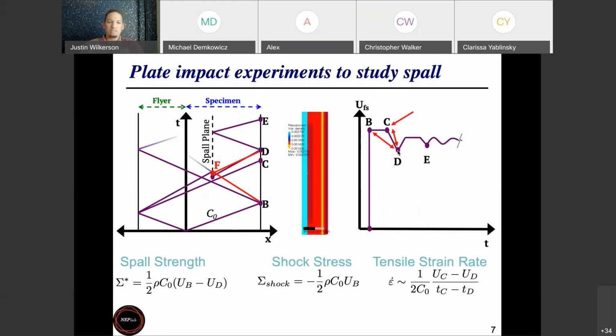And so we can vary a number of conditions to study spall strength under different conditions. Obviously we can launch the flyer plate at different velocities, and higher velocities are going to generate higher and higher shock stresses. So that's the main way that we control shock stress if we want to understand how shock stress affects spall strength. The main way that we control strain rate is actually through the thickness of the flyer plate material itself, or the flyer plate target. If we make the flyer plate target smaller, that allows less time for these rarefaction fans to spread out. And when they stay more compact, then you go from that highly compressed state to the highly tensile state faster. Okay, so this rarefaction fan is basically the time over which you go from the highly compressed state to the tensile state. So a thinner flyer plate is going to tend to give you a higher strain rate.